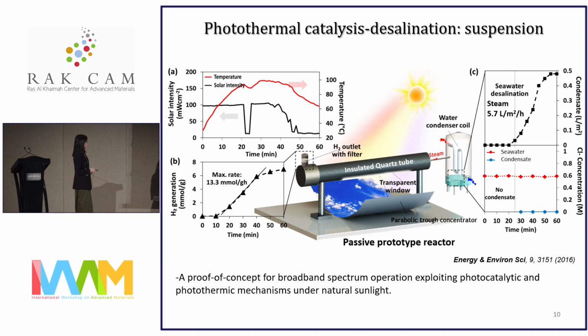Then we went on to design a passive prototype reactor, which has a parabolic trough that focuses the sunlight to the bottom part of the quartz tube, whereas the rest of the quartz tube is insulated to prevent excessive heat loss. And we have a hydrogen outlet with a filter that separates the water vapor from the hydrogen. The steam has not gone to waste. It's condensed into water at the condenser unit.